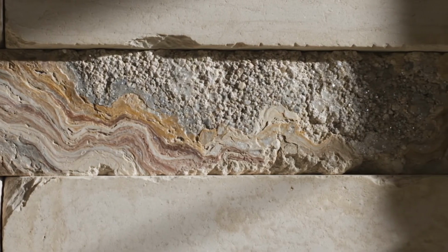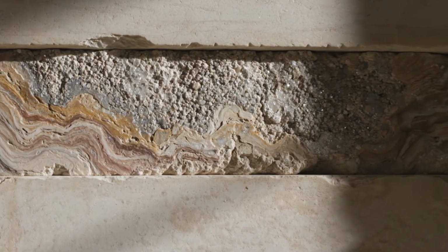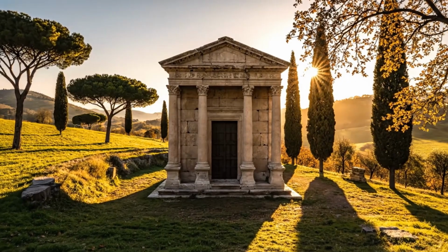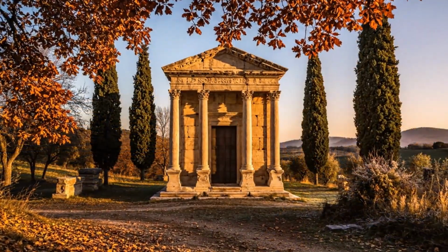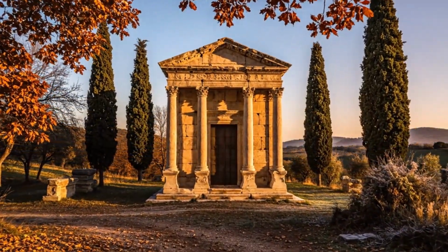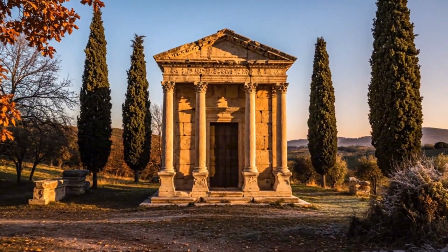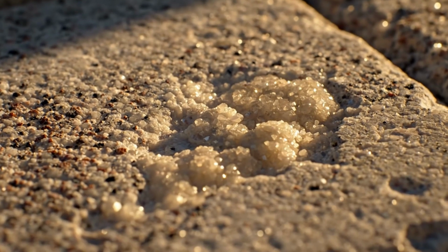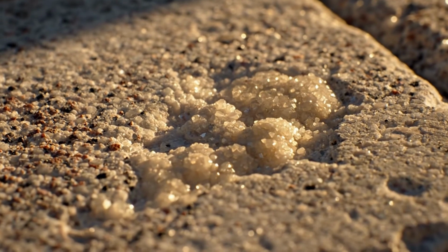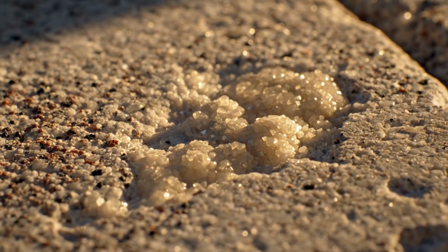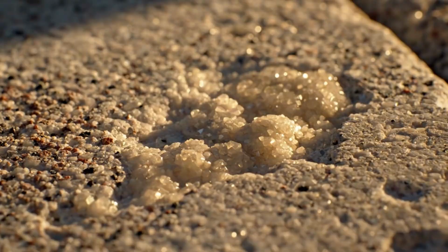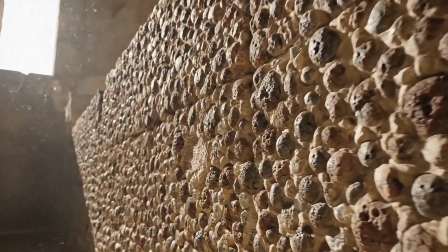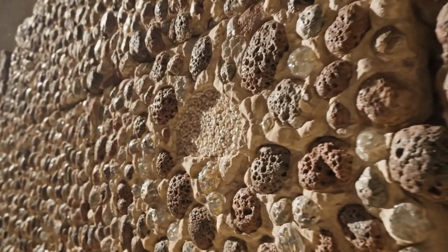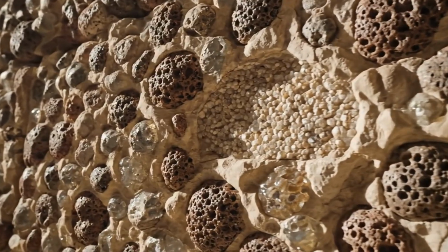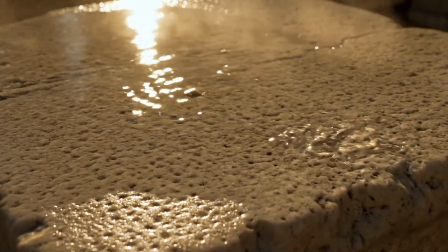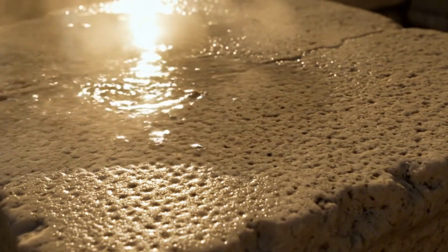Yet within the Tomb of Caecilia Metella, the presence of potassium appears to have had a different consequence. Rather than triggering destructive expansion, the released potassium contributed to a reorganization of the CASH binding phase. Researchers observed domains within the mortar that exhibited a refined nanocrystalline character. These remodeled regions suggest that the binding matrix had been altered at the microscopic level, developing new configurations that enhanced cohesion.